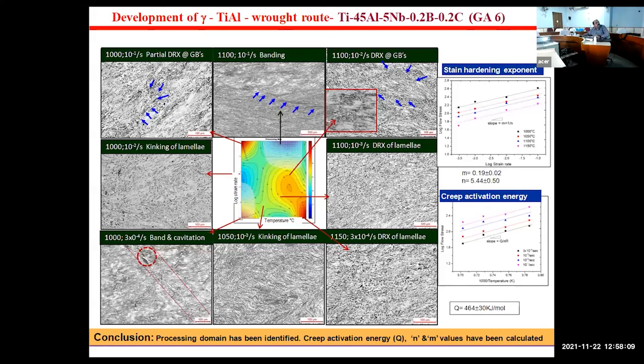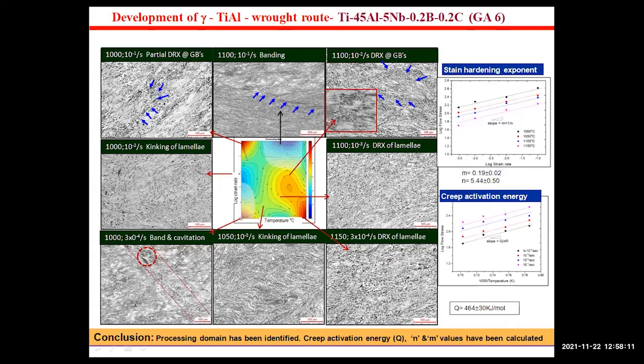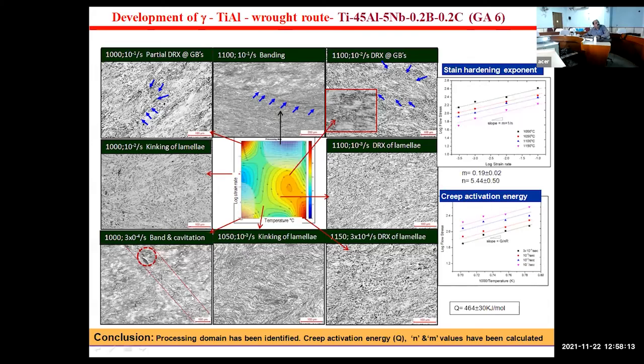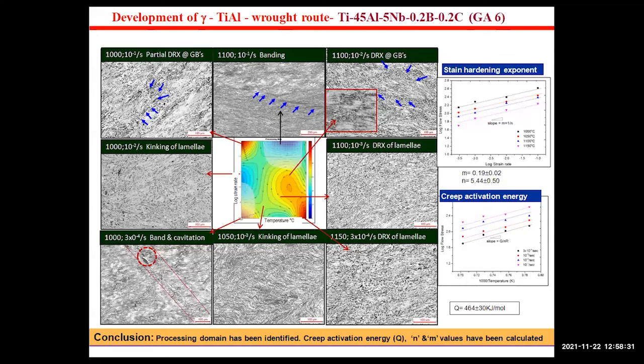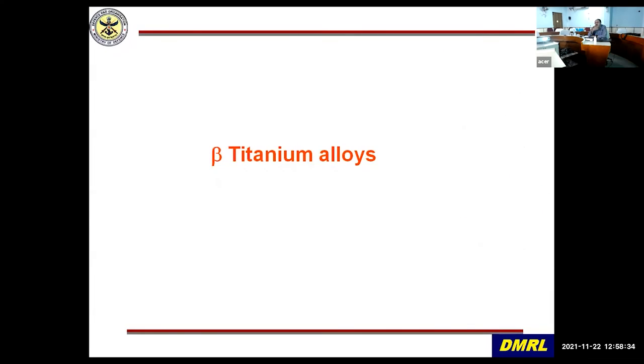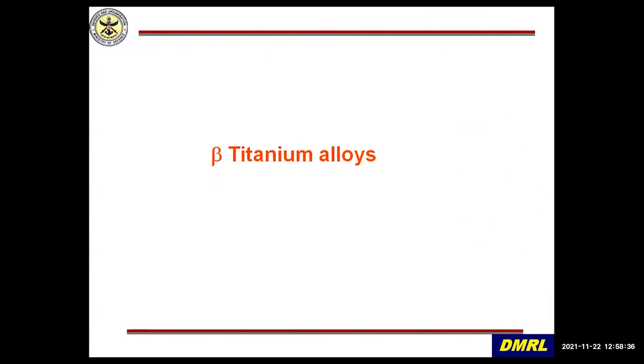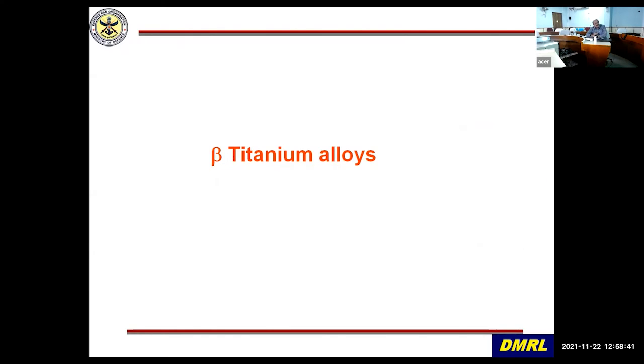Here a processing map of a particular composition was studied, and the region was identified where good microstructure can be obtained, because DRX, dynamic recrystallization, happens if you process in a good region. That is what we are trying to identify, whether we can also wrought form certain blades and all. So there is a lot of scope for research in these areas.